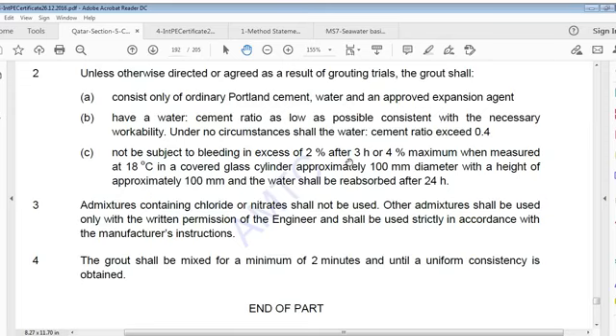So there were 3 points in grout. Consist only of ordinary Portland cement, water, an approved expansion agent. Have a water cement ratio in no case more than 0.4. Not be subject to bleeding in excess of 2% after 3 hours or 4% maximum when measured at 18 degrees Celsius in a covered glass cylinder approximately 100 mm diameter with a height of approximately 100 mm, and water shall be reabsorbed after 24 hours.